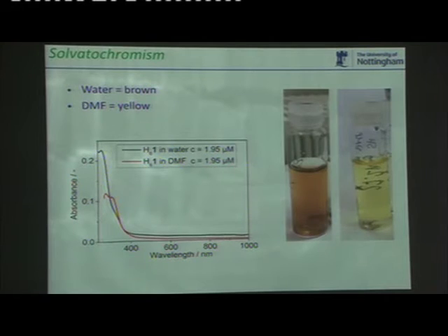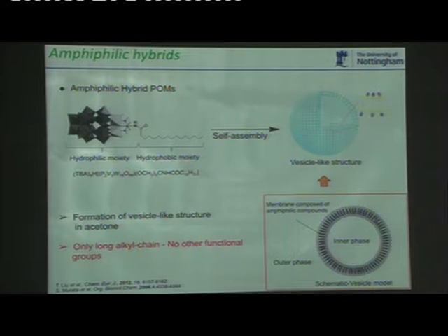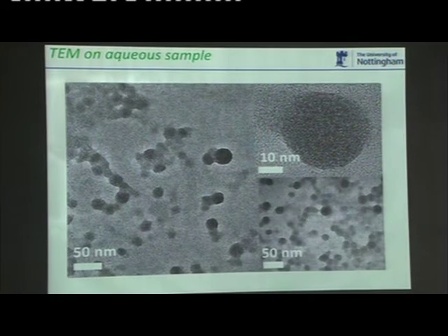Now, quite a lot of work's been done on this in polyoxometalates before, looking at the supramolecular assemblies of it. So, you know, you can form micelles and vesicles and so on. So we were pretty sure that that was likely what was going on. And indeed, when we took our polyoxometalate, and it was an acid, so H6 POM, we added it into water, and we could see that after gentle heating, we formed fairly uniform micellar assemblies, which are probably vesicles, but some soft assemblies.